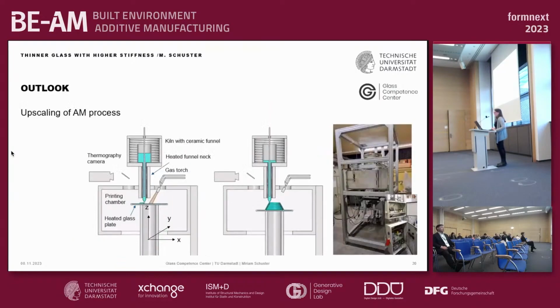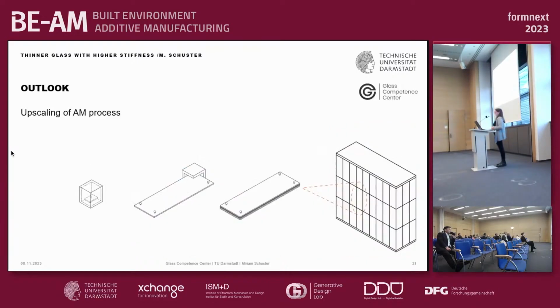Now coming to the outlook, at the Glass Competence Center we are currently building a glass 3D printer which is using the FDM method. And in this printer, we see it here in this picture, we are able to print on a base plate with the measures of 200 times 300 millimeters. This is the first version of a 3D printer. We are already planning the second version, where the aim is to print on a base plate with a size of 500 times 1000 millimeters. However, this is still small, so our vision is to go for very, very large printers, to be able to print on the largest glass panes that are currently available with 3.20 times 20 meters.